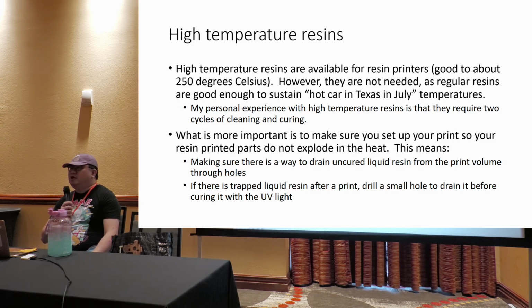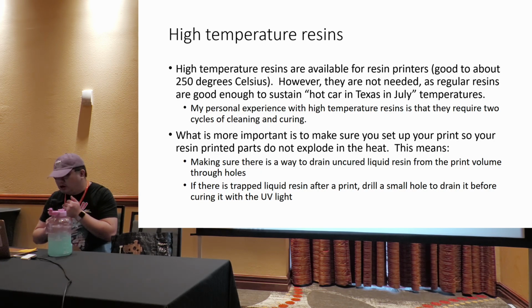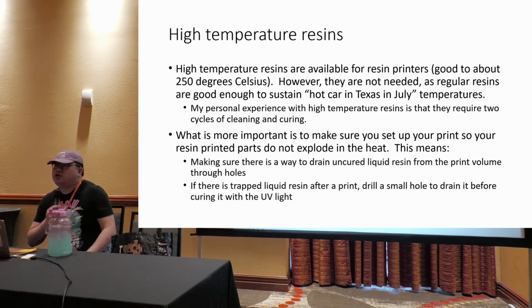These resins are available for use in resin printers. They go up to about 250 degrees Celsius. That's the number I've read. You don't actually need these to have the parts survive a hot car in Texas, really. The regular resins are good for about 150, 160 degrees Celsius easily. So you really don't need the high temperature resins. When people have a bad experience with resin prints in a car, it is actually caused by a different issue.